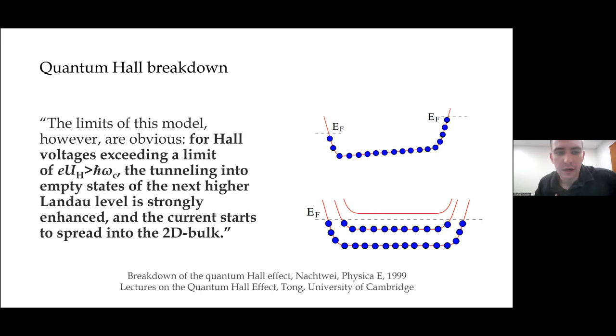I think the simplest one, in my opinion, is to just understand it in analogy to the quantum Hall effect. So the quantum Hall effect also has this current-driven breakdown regime, where as you flow a large current through your chiral edge state, eventually current spills into the bulk, and you realize a system without quantized anomalous Hall resistance. In that picture, as you apply a voltage, eventually you apply so large a voltage that there is a substantial difference in chemical potential on different sides of the device.